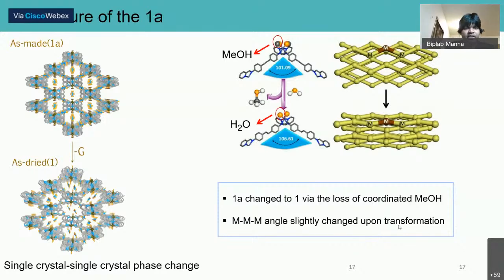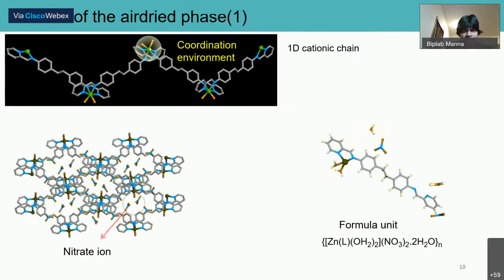Not only this, in structure 1 we could observe, as expected, that water is binding here in the coordination environment, and the structural organization changes a little. As you see, the pore is almost squeezed after loss of guest molecules. And this is the formula unit where water comes in place of methanol. We didn't perform theoretical calculations, but we can say this state is very, very energetically favorable compared to the original phase.